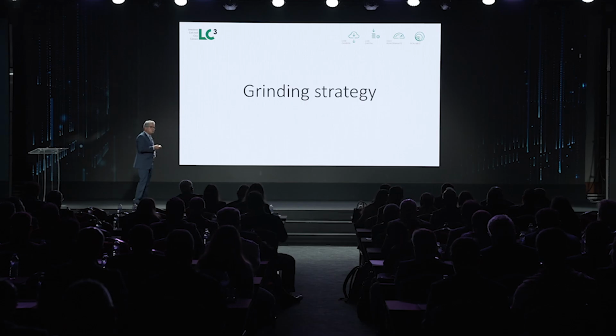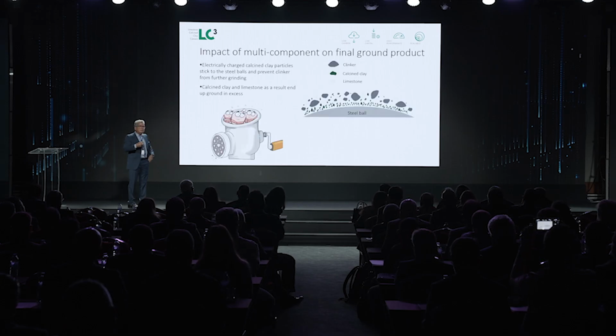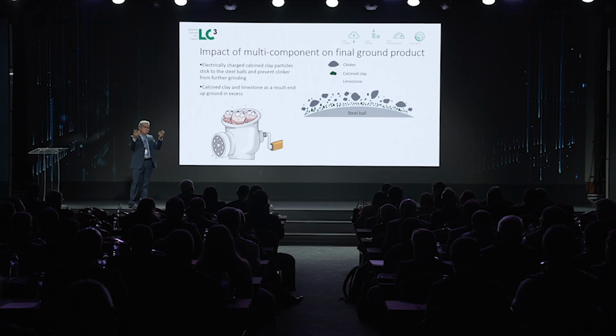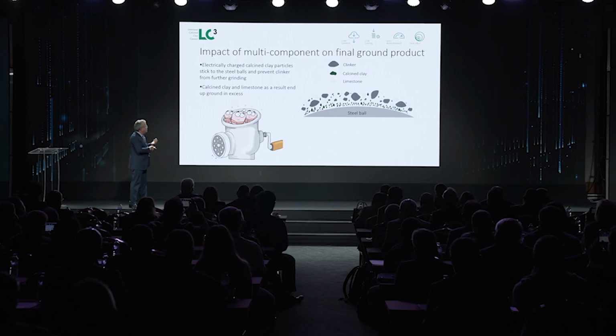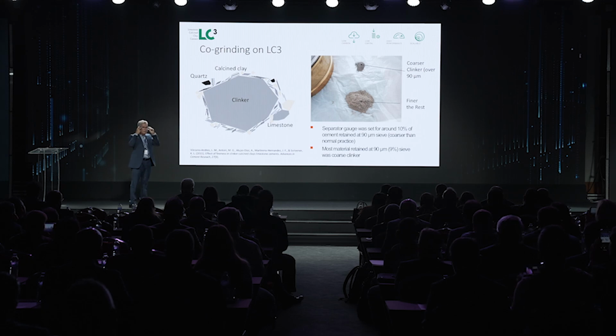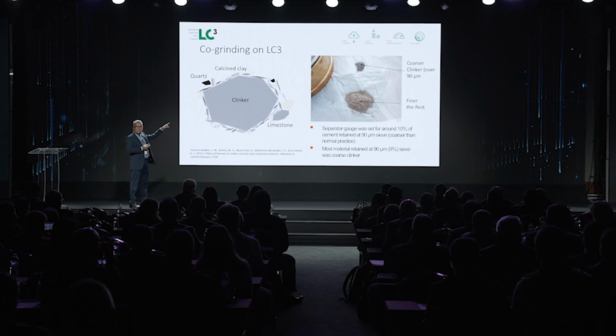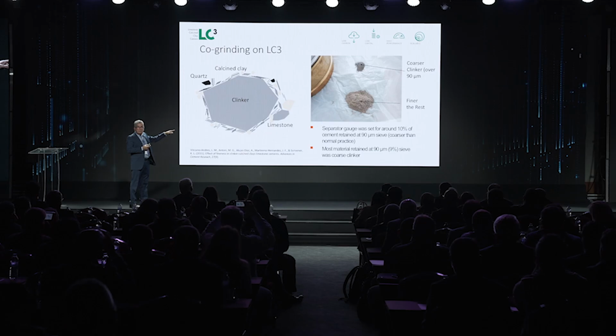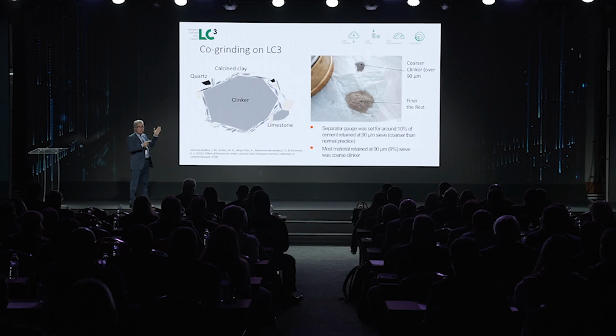In terms of grinding, this is also challenging because we're having a ternary binder. You have many products at the same time, different hardness of these products, so you can have over-grinding or under-grinding of some materials. When we ran the first industrial trial, this is the residue on the 90 micron sieve, and we were having the clinker very coarse, and we were having the calcined clay very fine, which is the worst case scenario, because you have a low reactivity in your system and you have a very high water demand in your system. But this is how we ran the first trial back in 2013. We didn't have the knowledge we have today.